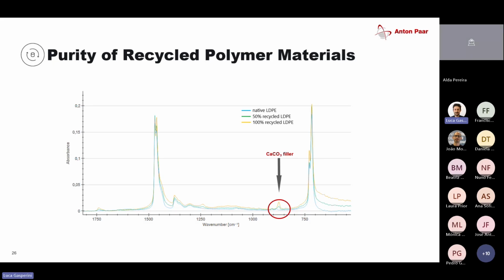So this was probably somewhere in the extruder, put into the formulation during recycling. This is a common effect you see in recycling, some calcium carbonate. And then we also have a CO stretching vibration. We are not quite sure, it's very hard to tell where this comes from, but we think that this is some ester bond which was created during the mechanical processing. And then last but not least, we also have another peak, which is the carbonyl group.